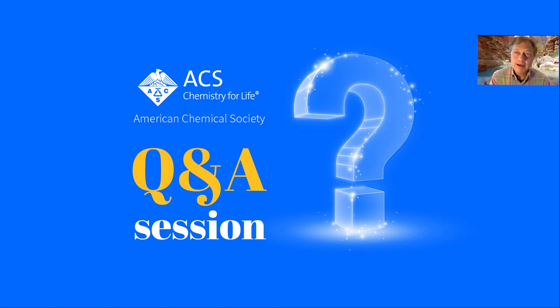Very early on, the idea was to use one sensitizer, a panchromatic light absorber that would harvest all the light. And then, not too much longer, say in the mid 90s, came the idea of using what they often called a cocktail, a mixture of different dyes, so that you weren't putting such a burden on each individual dye. There are challenges with that. Sometimes the dyes interact with one another in an inefficient way. But the highest efficiencies that I'm aware of now are for a porphyrin sensitizer with a bis isothiocyanate dye. I should say the highest confirmed efficiencies I'm aware of.